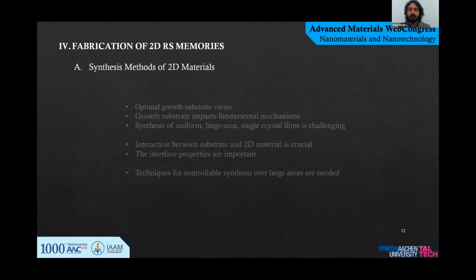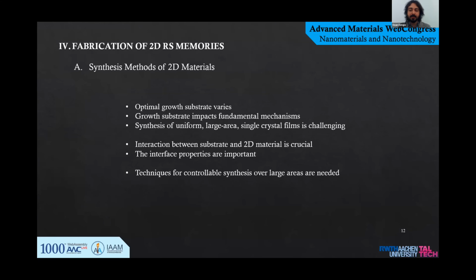For the synthesis methods, the optimal growth substrate varies with the chosen 2D material. This choice of growth substrate impacts fundamental mechanisms. The synthesis of uniform large-area, single crystal films over substrates, where epitaxy or templating is required to orient domains, is still a challenge. But understanding the interaction between substrate and 2D material, as well as the interface properties, is very important for quality. To have a full potential heterostructure, techniques for controllable synthesis over large areas where interlayer interfaces are maintained must be developed further.